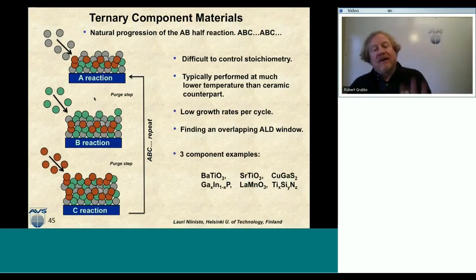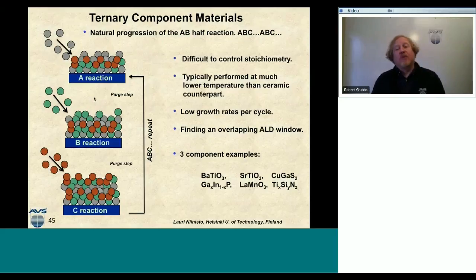These materials can be grown at a much lower temperature than their ceramic counterparts, but their ceramic counterparts are much higher quality films. The growth rates for these are typically much lower per cycle, and the challenge is to find the overlapping ALD window for each of these half cycles, or third cycles, excuse me. So we need a temperature where all three of those chemistries happen efficiently enough to give us the right stoichiometry. That can be a challenge. Some might work at higher temperatures, some at lower temperatures, so finding that common overlapping temperature ALD window can be a little tricky for these materials.